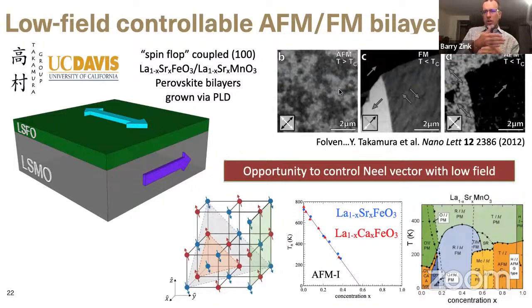That's a particular arrangement of those two magnetic order vectors that she refers to as a spin-flop coupling or a spin-flop arrangement. I know spin-flop gets used for other things too, so sometimes it's confusing for people. But the idea is that these two vectors are quite rigidly coupled to each other, and you therefore can manipulate the antiferromagnetism by applying relatively modest fields to the ferromagnet below it, and move around the Néel temperature, or the Néel order, which was a very cool idea, it seemed to me.